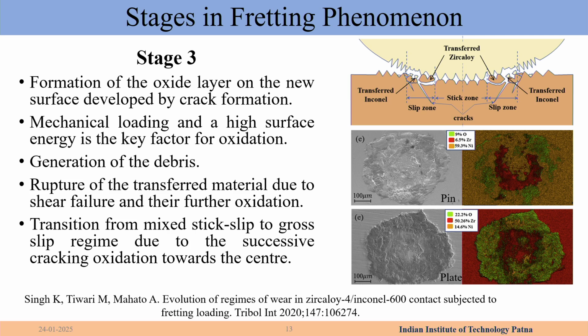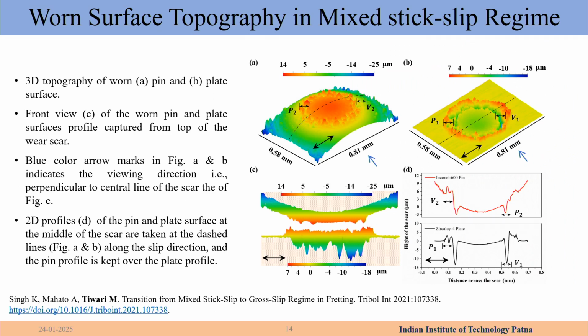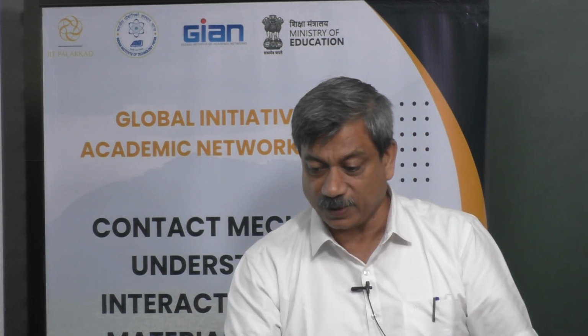So we've seen this from the characterization of how much oxygen there is in the stick zone and slip zone. And then the worn surface topography. The interesting thing is this is the pin and this is the plate, the zircaloy plate, Inconel pin. It's like a mating part, completely the negative of this. So you can see at the edge of the stick there are deep protrusions in the pin, and there are deep valleys at the same point in the plate. These actually create a negative of the hole, which makes sense, but you can see how much damage happens and where it is happening, at the edge here.